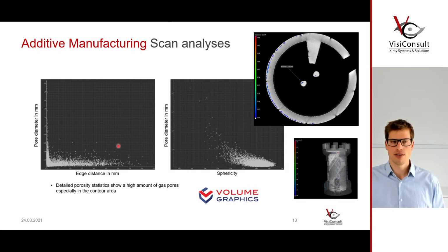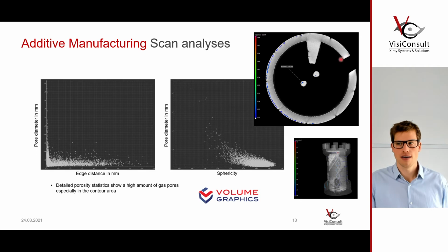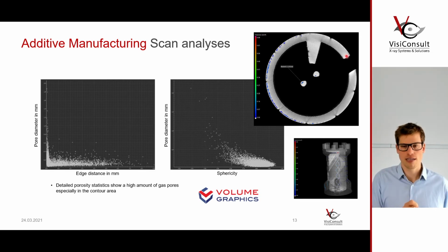There's a reason, because in many cases you are first lasering or sintering, at least when you use selective laser melting or sintering, you sinter the outside of the part to create a more hard shell. And then you do cross-hatching on the inside, which is done with a different beam intensity.